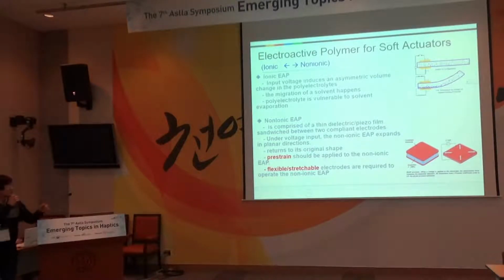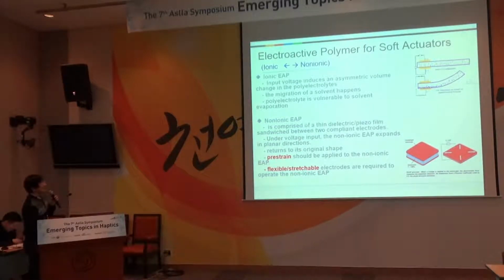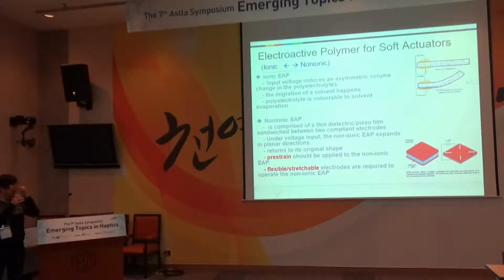Many people focus on the non-ionic EAP. It consists of a thin dielectric or piezo film sandwiched between two compliant electrodes. Under voltage input, the non-ionic EAP expands in the planar direction and compresses in the thickness direction. As soon as we remove the voltage, it returns to its original shape very quickly, so it can create a strong vibration. But the problem is that pre-strain should be applied to the non-ionic EAP, and a flexible or stretchable electrode is required to operate it.